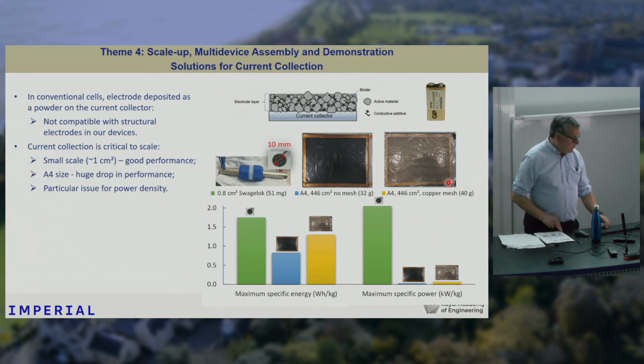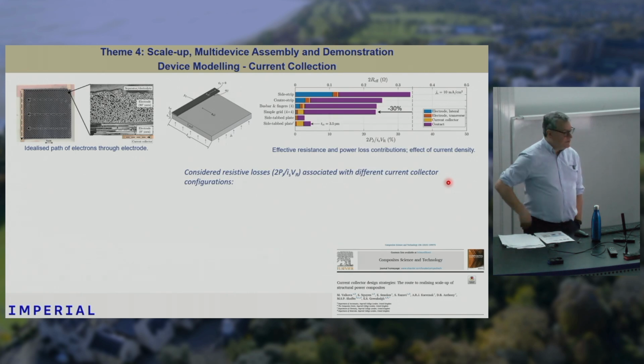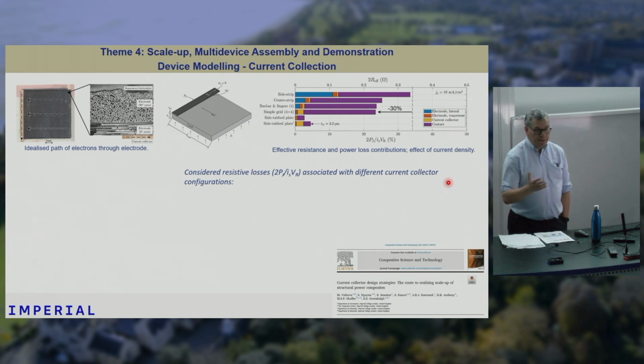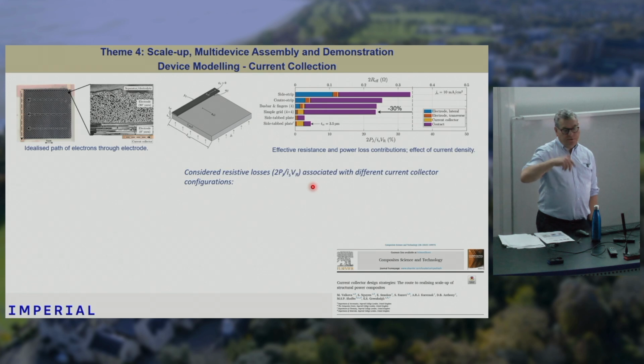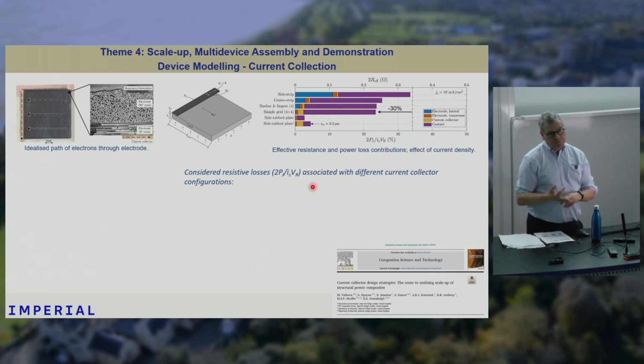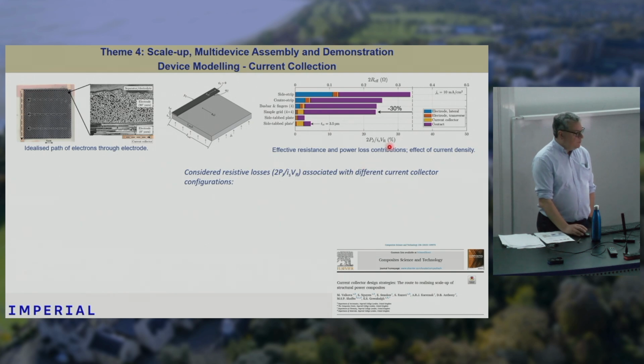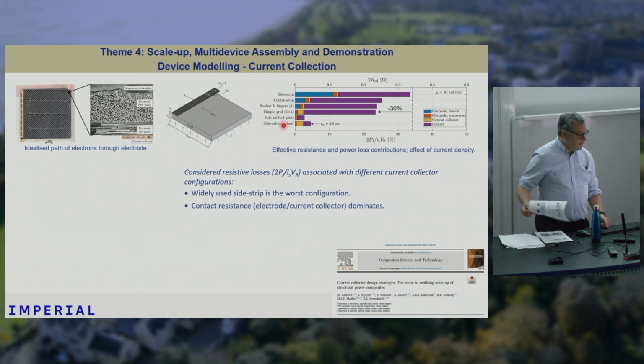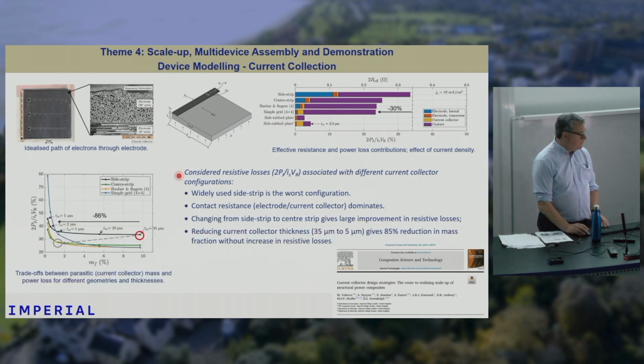So we've started, well, we had some work on current collection, where we started to model this, just using Abaqus with the electrical model in there. We characterize the different resistivities associated with the system. So there is an in-plane resistivity, a through-thickness resistivity, a contact resistivity between the current collector and the electrode, and then the inherent resistivity of the current collector itself. And then this is showing you for different configurations of current collectors. So this is a side strip. You could put the strip down the middle. And in fact, if you do that, you actually get quite a saving in terms of reduction in electrical losses. And then started to play around with different configurations to give us different balances. So if I move on to this slide, which is showing you the percentage weight of the current collector against the resistive losses.